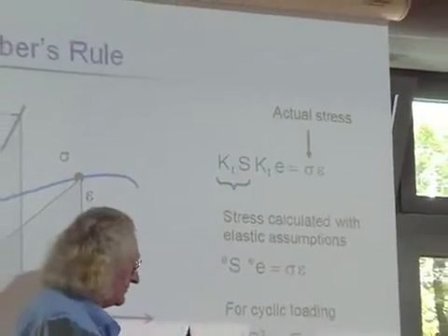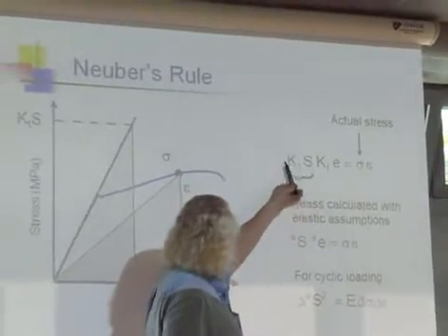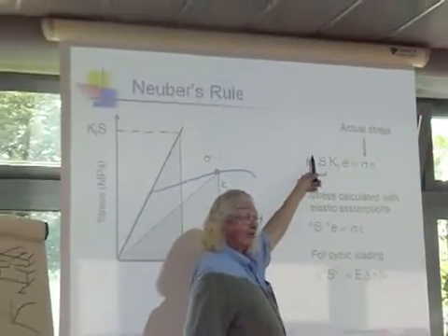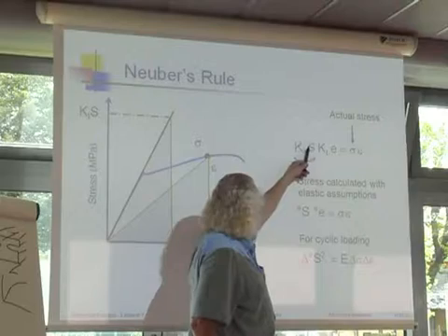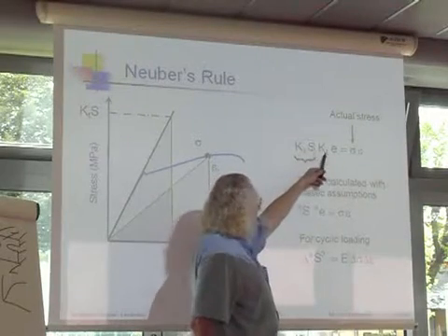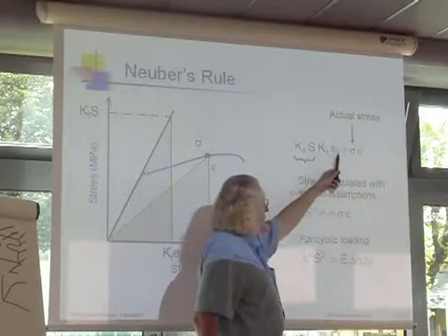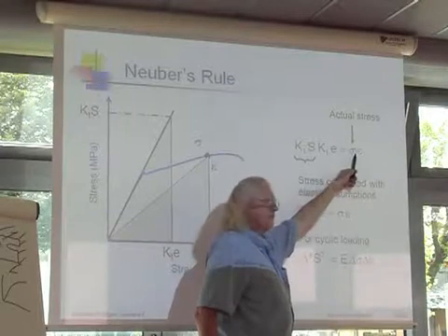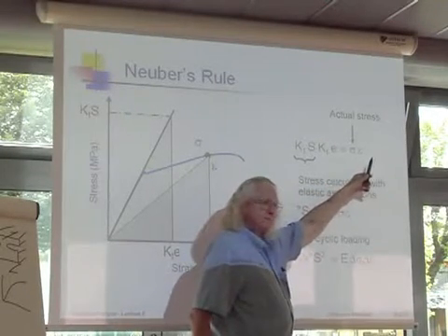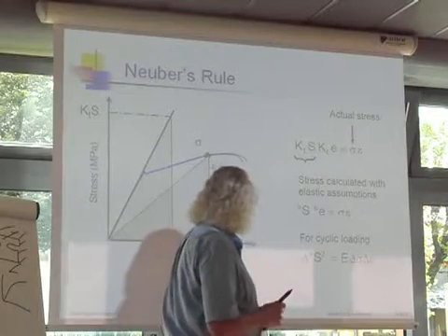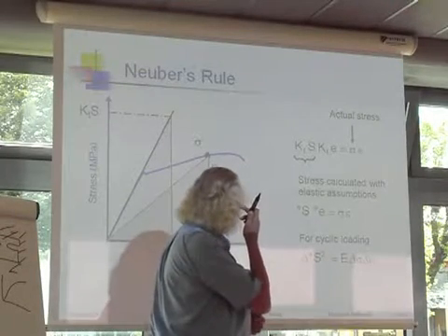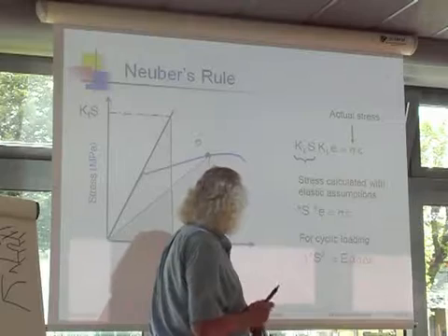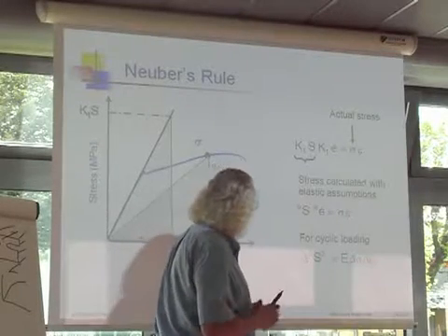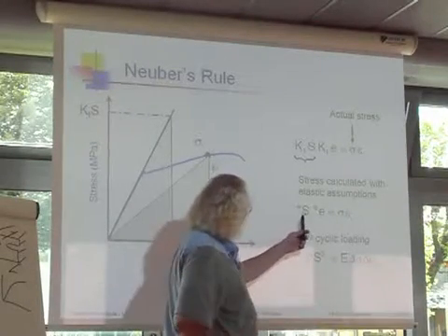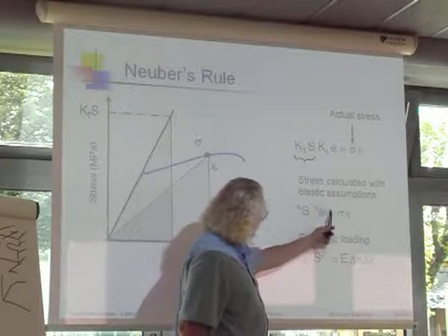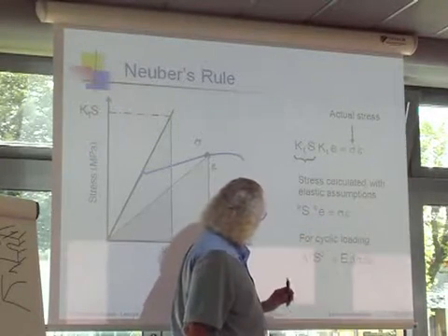in this mechanics, strength of materials approach, but this could just be the elastic stress that comes from the finite element model as well. The product of the elastic stress you calculate times the elastic strain you calculate is equal to the product of the real stress and the real strain. And that turns out to be very, very powerful. And, well, since it's an elastic model, stresses are calculated with elastic assumptions. And so I have this elastically calculated stress and strain are equal to the real stress and strain.